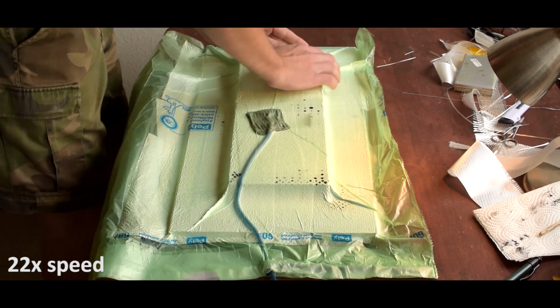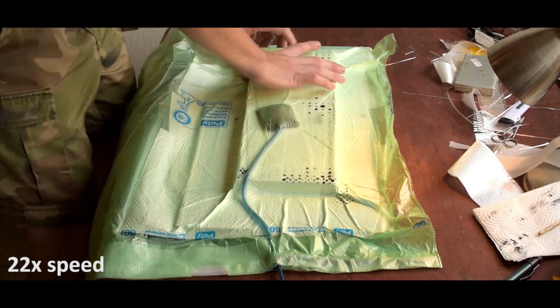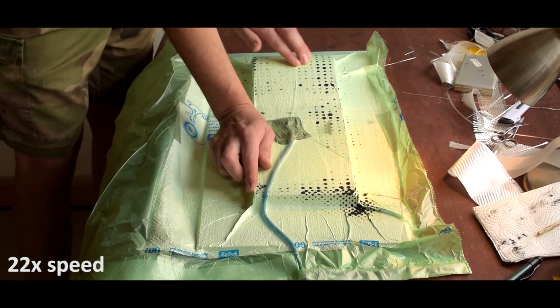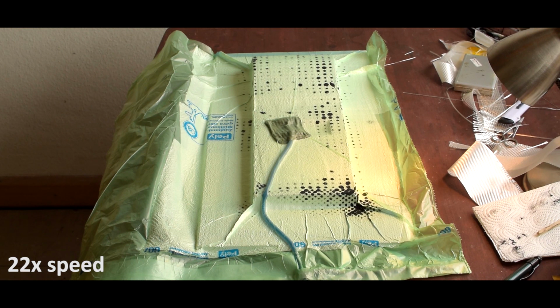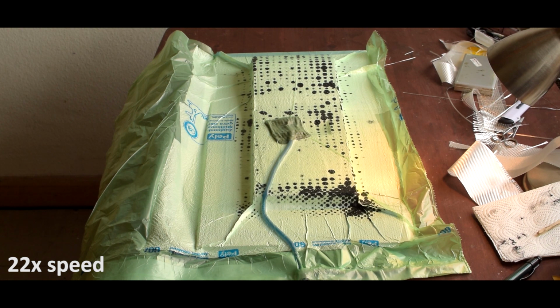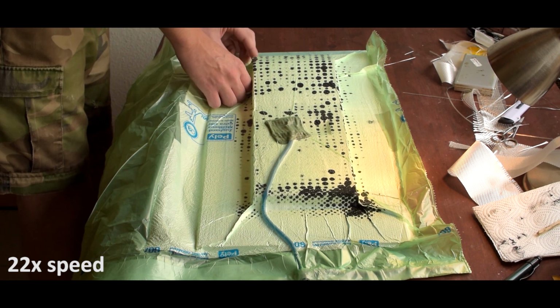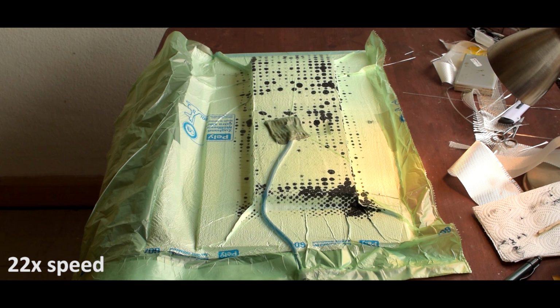Now you see the atmospheric pressure pushing the bag tightly against the mold. Where the black dots appear, excess resin is soaked through the peel ply and the release film. In between, I shut off the pump to be able to further squeeze the vacuum bag into the edges of the mold. By the way, I use ordinary garbage bags for vacuum molding, I just make sure they are really airtight. Afterwards, I left the pump running for at least 8 hours.